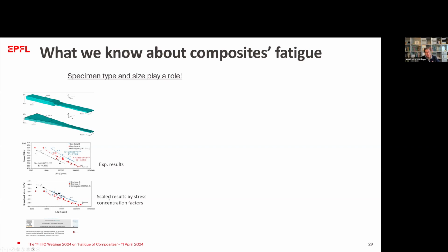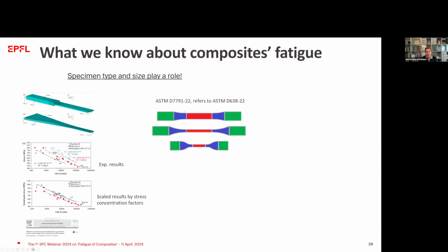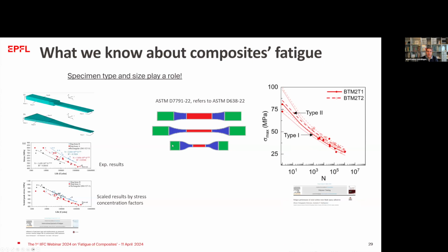So the result from this paper is that if you consider the stress concentrations, you can alleviate the stress concentration in the rectangular specimen, then you can probably have a rectangular specimen that gives good results. We also, as I said before, did some tests following the ASTM standards for adhesives, so polymers, and using 3 different types of specimens, we realized that the result, especially in fatigue, is not the same. Although the standard suggests that you can use either type 1, type 2, or type 4 specimen for doing the testing.